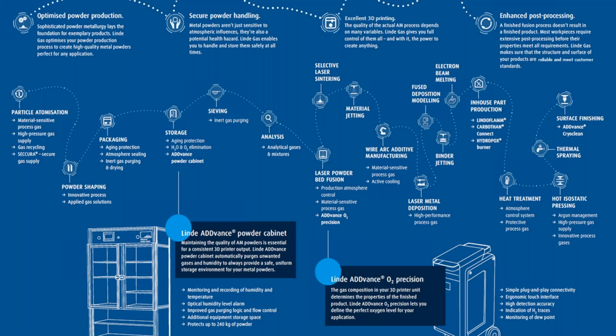the aging process, and atmosphere sealing. So one of the problems can be moisture or contamination inside the powder itself, and the powder itself can be somewhat dangerous depending on how fine it is. You don't want to inhale or breathe any of those things. So Linde has some products, powder cabinets, that allow for a controlled atmosphere to preserve those powders as they're being transported or stored on site.